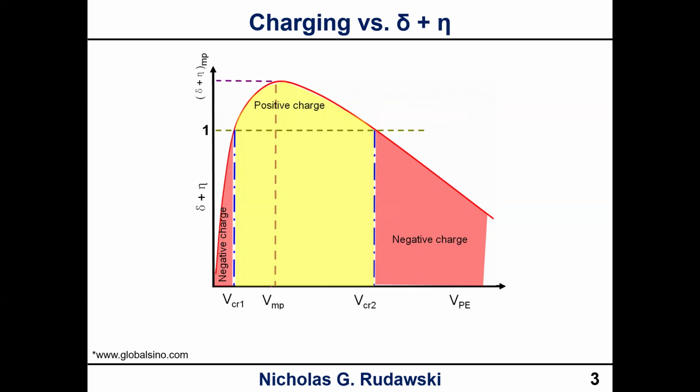You can see this schematically in this plot, which plots the yield as a function of electron voltage. Again, we're assuming a semi-infinitely thick sample that is not grounded. So we can have a net negative charge up to some voltage, at which point the yield goes to 1, and then at that point my net charge becomes positive.